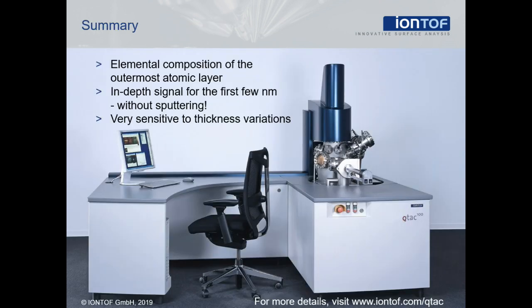In summary, in addition to the composition of the outermost atomic layer, LEIS provides the in-depth information of the elements over the first few nm of the sample. This information is gained without sputtering the sample, and by avoiding sputtering artefacts, this approach is ideally suited for the analysis of ultra-thin layers — even those below a nm in thickness. The thinner the film, the more sensitive LEIS is to small variations in layer thickness. For more information, please visit www.iontof.com.